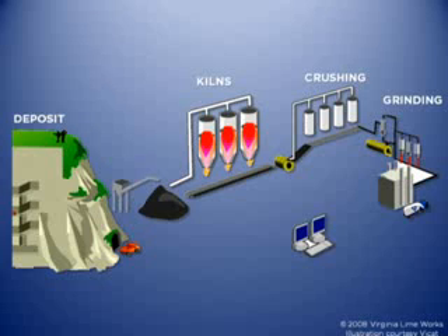But what we have here, you have a deposit, a raw limestone deposit that's extracted. It goes to the kilns where it's cooked. The resultant quicklime, if you want to use the term, or burnt cement rock, is then crushed and ground up, where the powder is shipped off. Now, this material is extremely hydraulic. If you add water to pure natural cement, the set starts to take place in about 3 minutes, and it is at a hardened state in about 5 or 7 minutes. It's extremely fast setting. At 28 days, if I'm not mistaken, you're looking at compressive strengths of upwards of 5,000 psi. So very, very hydraulic, very, very tough stuff.